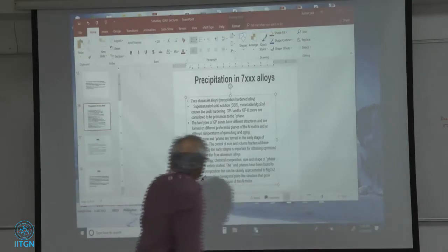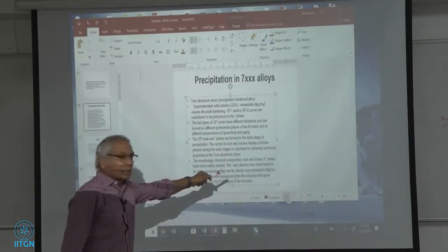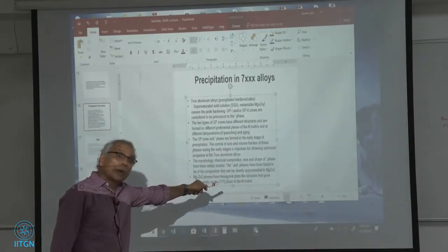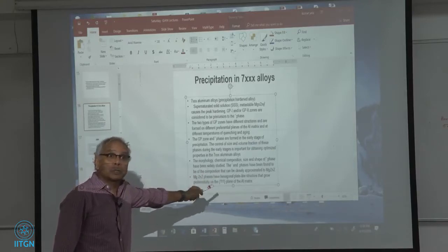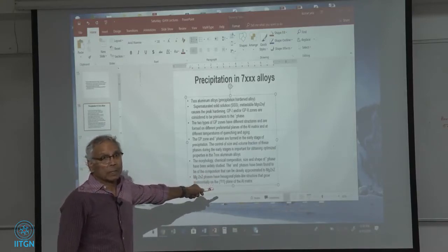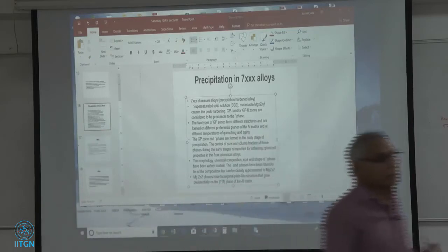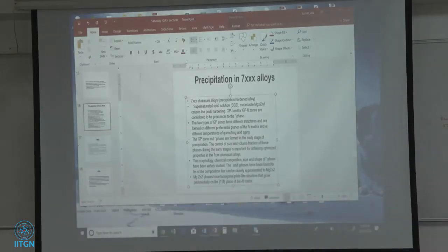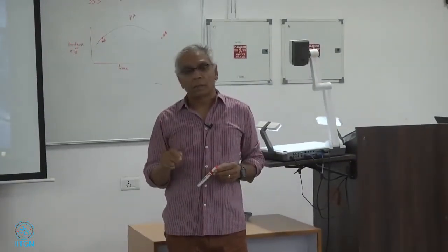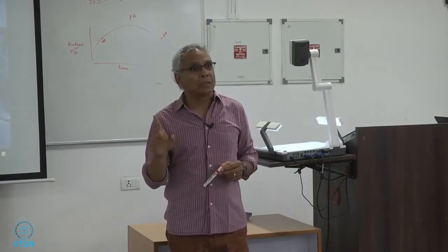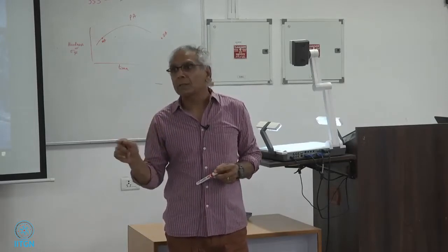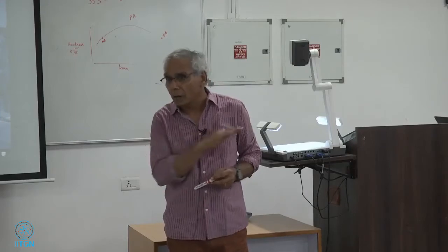And the only thing is, this is important, they're hexagonal plate-like structures and forming on the 111 plane, because that happens to be the slip plane for aluminum. Okay? So they're sitting on this slip plane. Remember always, 111 is the slip plane for aluminum alloys. All aluminum alloys. 110 is the slip direction. All FCC materials.